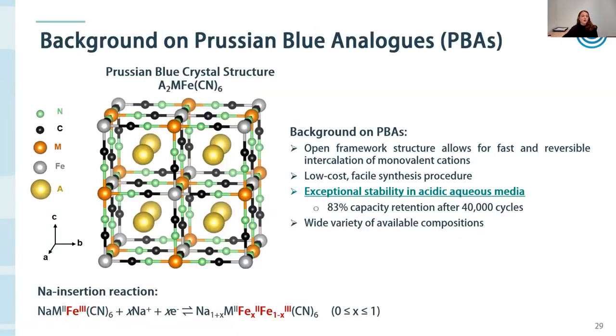Prussian blue analogs have this open framework crystal structure, and they're made of these ferricyanide groups and a divalent transition metal ion like copper, nickel, manganese, cobalt. There's quite a few different types of Prussian blue analogs. The really important thing that I want to point out is because of this open framework structure, Prussian blue analogs can really easily intercalate and deintercalate monovalent cations like sodium. And they've shown really exceptional stability in acidic aqueous media, over 40,000 cycles with very little loss in capacity.